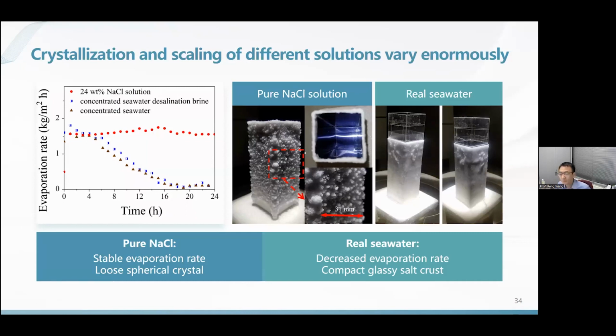The system worked perfectly. And you can see, we have a very stable, continuous evaporation rate. And you can see from the photo in the middle part here, we have beautiful spherical aggregates of sodium chloride. It was great. However, when we switched the test solution from the pure sodium chloride solution to real seawater, guess what happened?